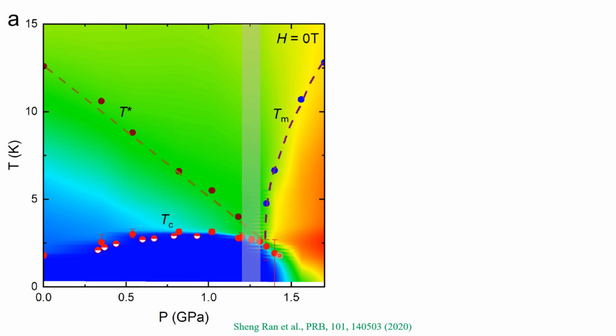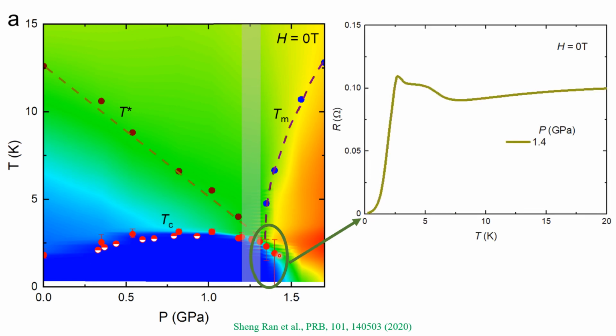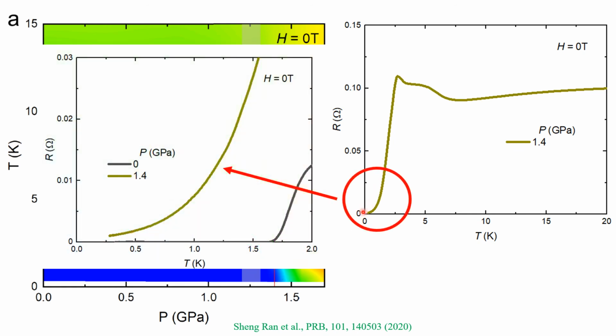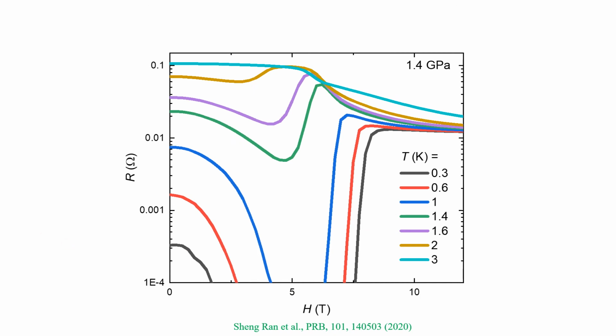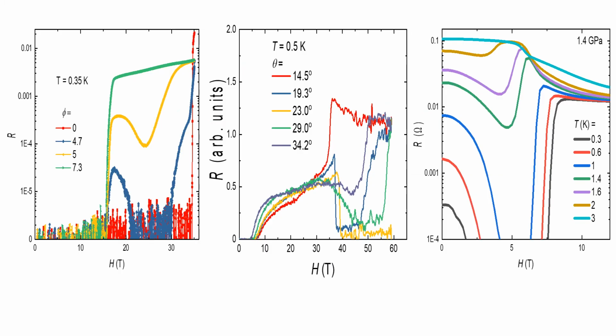There's a region where superconductivity coexists with this magnetic phase. Here we see an anomaly associated with the magnetic phase, and then a resistance drop at a lower temperature. But if we look closely, resistance actually does not go to 0. It becomes very small, but does not go to 0. At this pressure value, if we apply magnetic field, resistance does go to 0. So field-induced superconductivity again.